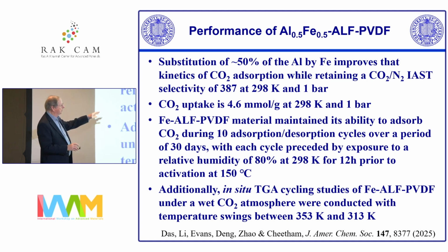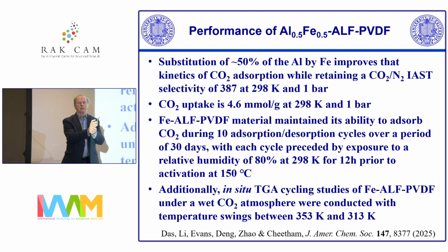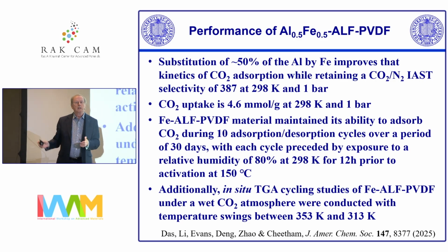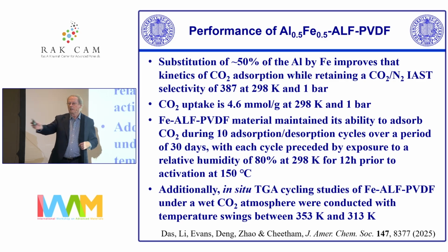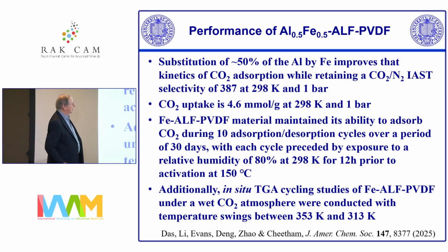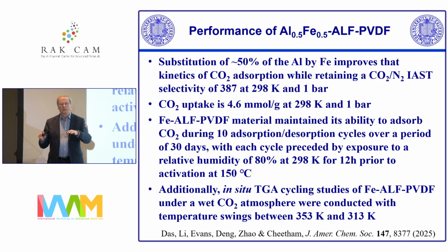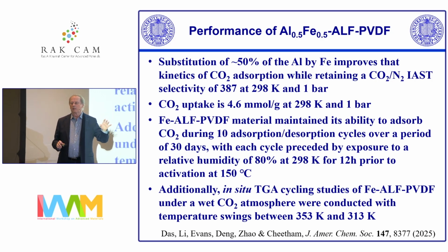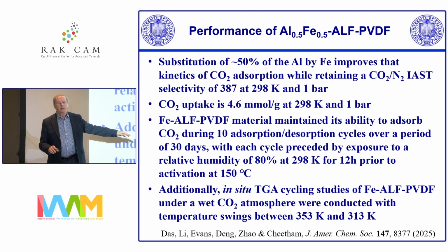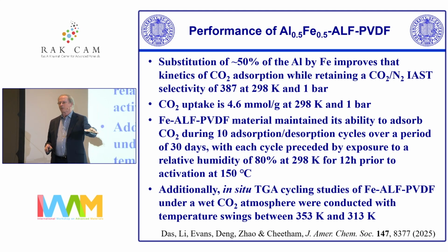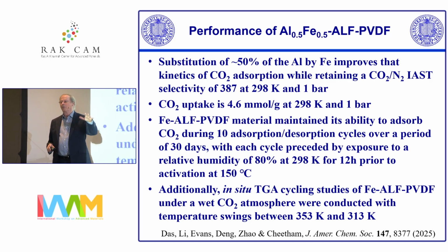And so we did, for example, cycling of the materials, sort of repeated CO2 adsorption, desorption, followed by heating it in a moist gas atmosphere and then repeating it. And we did that for about 10 days, and there was no diminution of performance. Having said all that, the flue gas is so difficult. You know, saying you can do it for 10 days is one thing. Doing it for 6 months or a year, which the companies who've got these plants will want to do, is a different matter. And I'm not confident that any of the MOFs are going to survive under those sort of extreme conditions, even ALF with the coating. But you can make it hydrophobic.